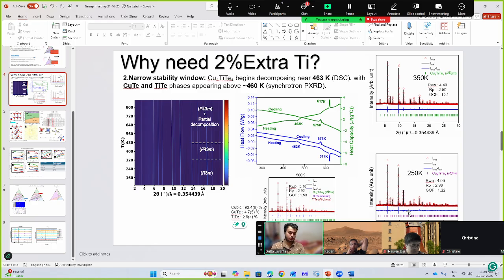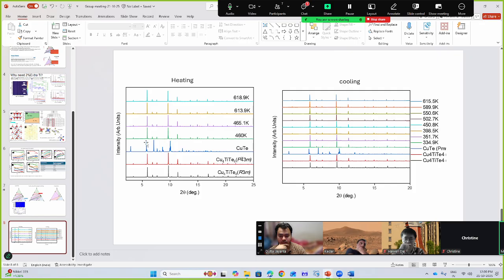Okay. I discussed with him. Try to find the sweet spot for the SPS. Density is like 95% and above, and you don't have too many precipitates. That's the trick. If I go high temperature, then when it cools down, again it's forming the phase. If the cool down is very slow, then there are more binary phases forming. Even this is also the synchrotron data. You can see in the cooling cycle, there is impurity.